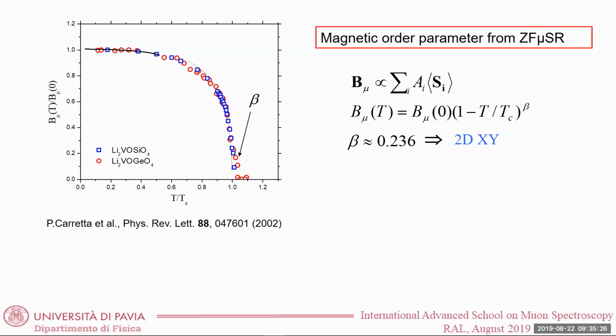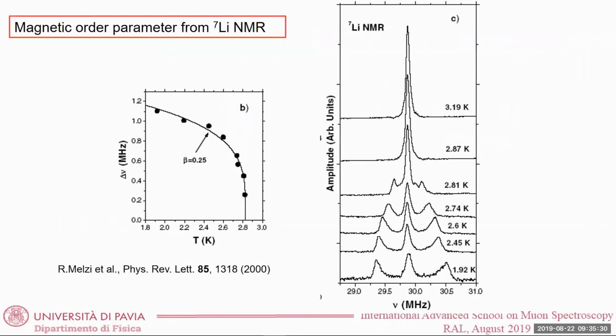And if you concentrate on the low temperature, for example, you can study, before going to the low temperature, this is to compare with NMR. In NMR, again, I have to apply a magnetic field if I want to make this study, okay? And if I apply a magnetic field, I will perturb the system, in particular in this case, where the system has an exchange coupling which is of the order of a few Kelvin. So it is a non-negligible perturbation with NMR. And the other point I want to make is that with NMR, to study the order parameter, what you're going to measure is the splitting between these NMR lines, which you can define not so well as you do for the μSR internal field. So you get a big error bar here with respect to the case of μSR.